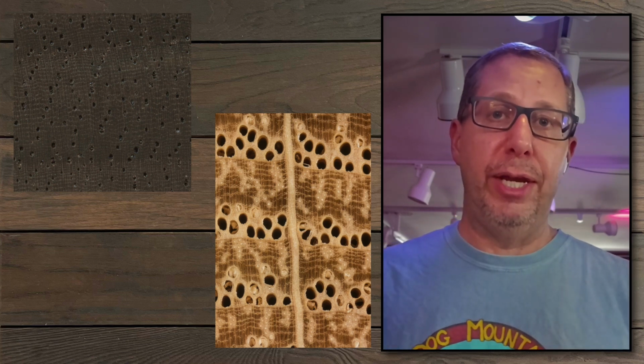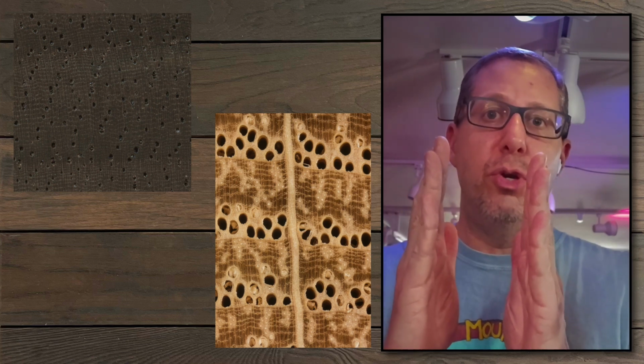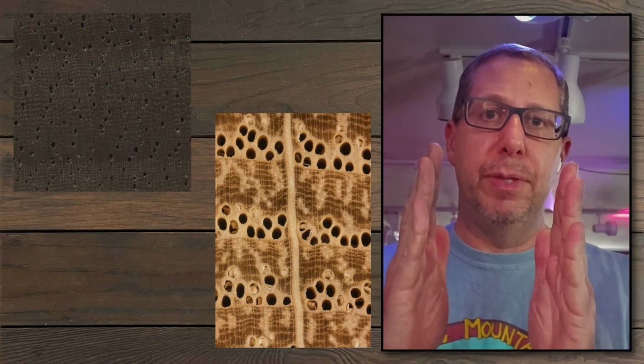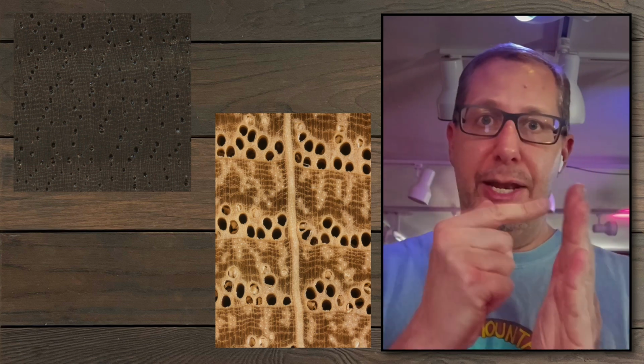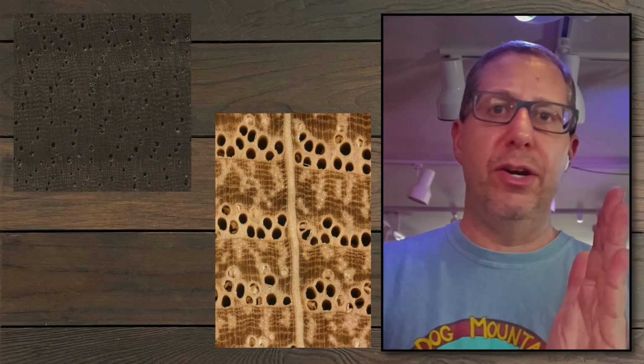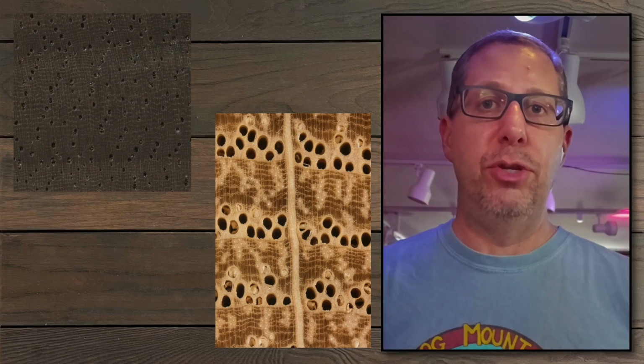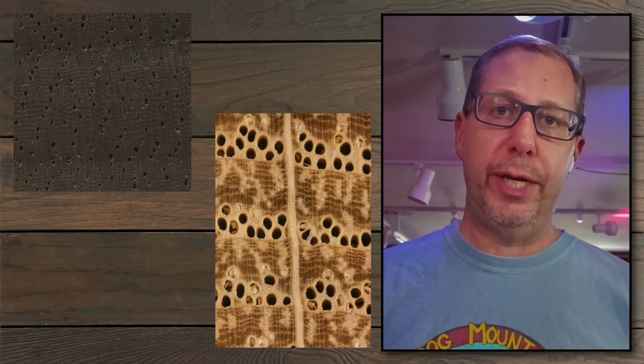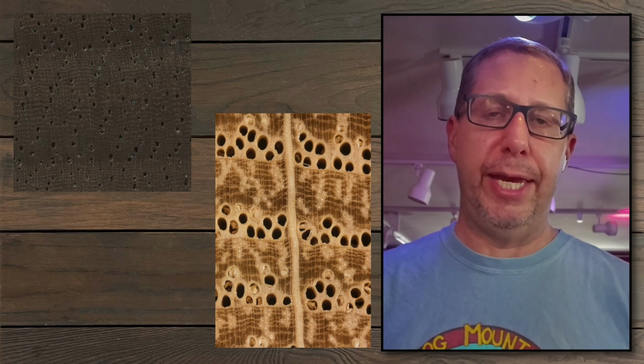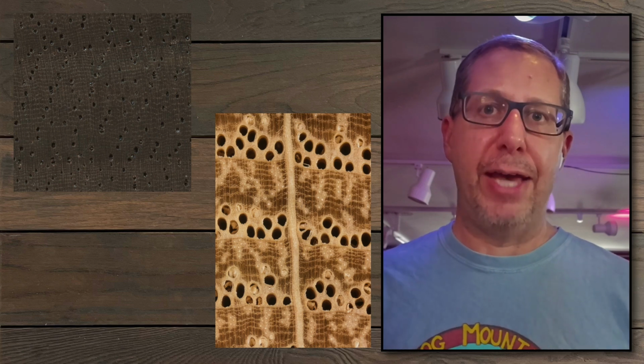Now, slicing an end-grain cookie, now suddenly I've got a 2-inch or 3-inch thick bit of end grain that longitudinally, the water moves like 100 times faster than any other direction. You can dry out an end-grain cookie really quickly, which is why they're so prone to checking and cracking, because of that fast moisture exchange.